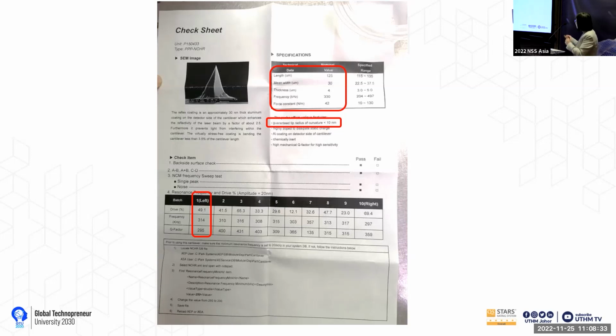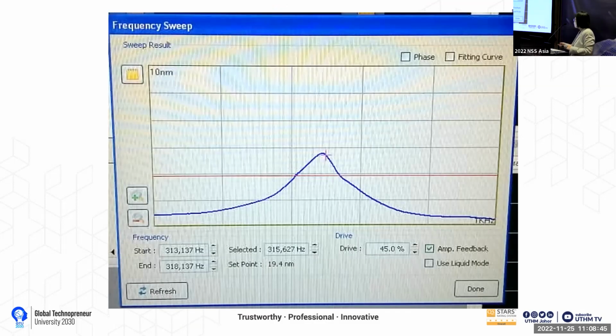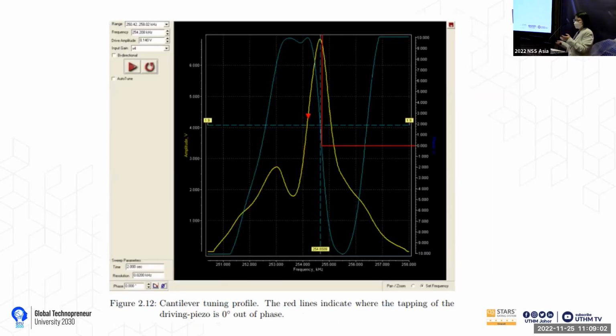Every tip mostly has a tip radius of less than about 10 nanometers. Another important piece of information is the force constant. Okay, I'll show you in a short while why this information is important. Usually the resonance frequency of the cantilever ranges between 200 kilohertz and 400 kilohertz. This is taken from our lab. This one has about 315 kilohertz resonance frequency. This is another example, a tip of about 250 kilohertz resonance frequency.